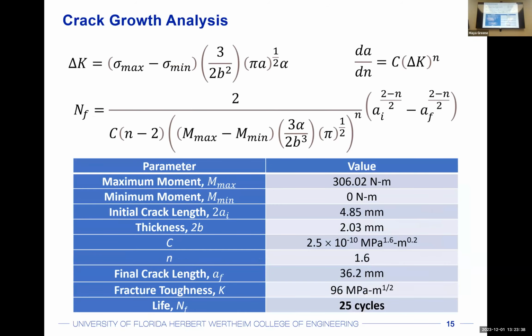In addition to this, since this was the load case we were most concerned about, we also performed a crack growth analysis. The crack growth analysis was performed around the rivet holes that were going to be drilled into the skin, and that was taken as a potential place where we might see crack growth based off of repeated impact. In this case, the moment at those points was calculated, and then taking that initial crack length, assuming the rivet sizes where we might see a crack form, we were then able to calculate, based on the material properties, the constants C and N for calculating a life during crack growth as well.